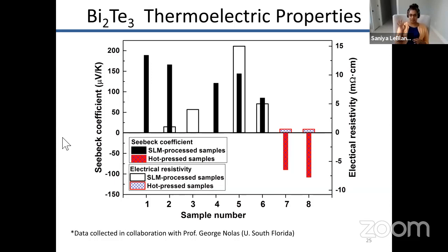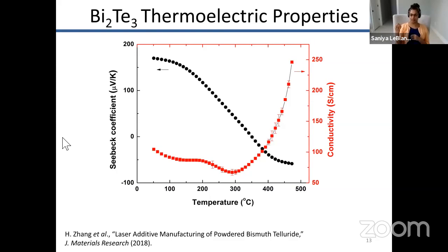So the kind of pinkish ones on the right are showing the traditionally melt-grown materials, and then the ones in black on the left are the laser processed materials. And what we see is that the Seebeck coefficient is a different sign. What that tells us is that we're starting out with a material that, even though traditionally it's an N-type material, when we laser process it, it's a P-type material. So it has a positive Seebeck coefficient. And what we find is that as we change the temperature, the material that starts as a P-type material, if you increase the temperature, you're increasing the number of donors, and it eventually does transition to an N-type material.